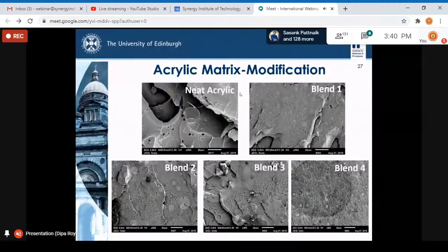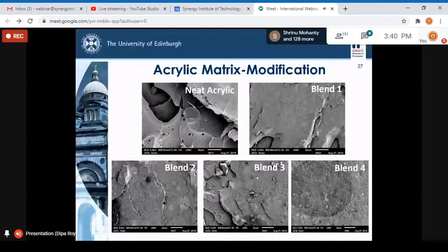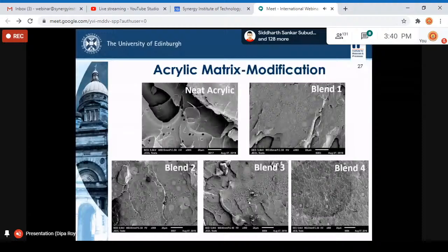I'm not sure if you can see properly. There are some small zones here, but they're very well bonded with the acrylics. Now, with the increase in the percentages from 3 to 15%, in this second phase, you can see how it looks quite different. But what we can see from these micrographs is that there is a very well bonded polyphenylene ether dispersed phase present in the overall matrix.